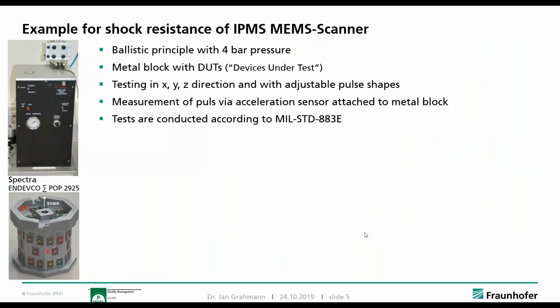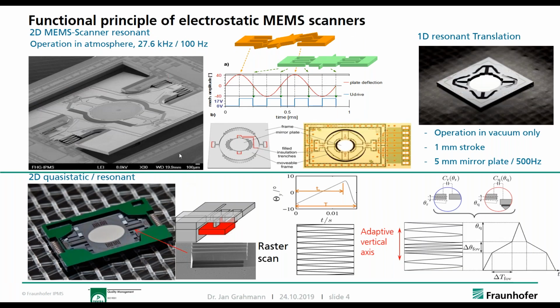Now I go one back. I have to mention that these mirrors, due to the bulk micromachining technology, are made out of single crystal silicon, which is a quite important property for us, because that single crystal silicon allows us to not have to look at fatigue of the mirror, for example. So we don't have any fatigue. And most important for us concerning destruction is the vibrational and the shock load onto the mirrors, which is of course not allowed to break any of these structures as shown here.